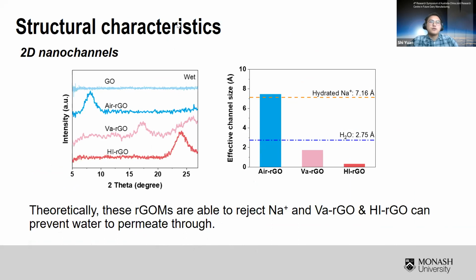Then we try to identify the structural characteristics. Firstly, the 2D nanochannels, which are well understood by other researchers. We can find that the effective sizes of this 2D channel are all similar to or smaller than the hydrated sodium chloride. So ideally, these three membranes can effectively reject sodium chloride. And for vacuum RGO and HI RGO, the channel size is even smaller than the water molecule. So theoretically, these two RGO membranes cannot allow water to go through. So let's see the performance we measured.